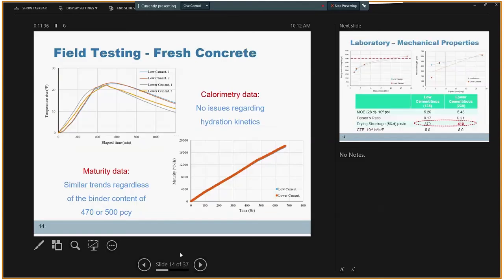The third category of fresh property testing we had was the calorimetry data and the maturity. The top graph presents the calorimetry data. We had 2 samples per concrete type, and it was observed that the concrete prepared with lower cementitious material generated a lower total amount of heat over time during the first 24 and 48 hours after casting. However, no significant issues could be observed here. We couldn't detect, based on the data, any potential problems with setting, delayed setting, or elongated setting time.